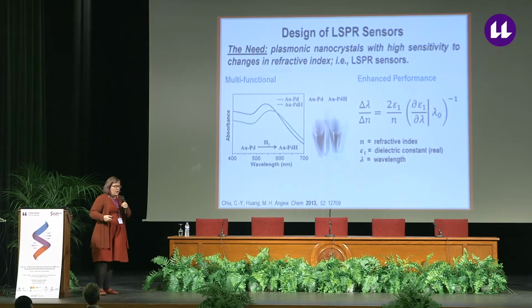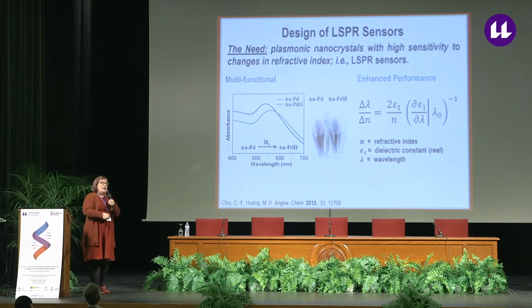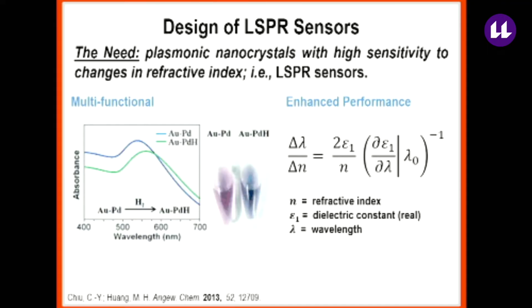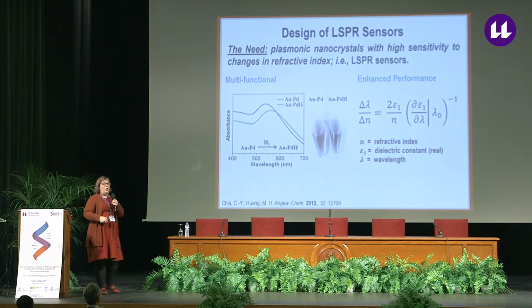But as I mentioned, I'm interested in whether or not there's some value to considering bimetallic compositions. And indeed, there are some reasons to consider it. One comes back to this idea of multifunctionality. And here's a nice example from Michael Huang's group where they took a gold core and put a palladium shell around the nanocrystal, and the palladium is able to dissociate hydrogen and take it up into its lattice, and the gold core was able to sense that change in environment, resulting in a shift in the LSPR, or color change of the solution.